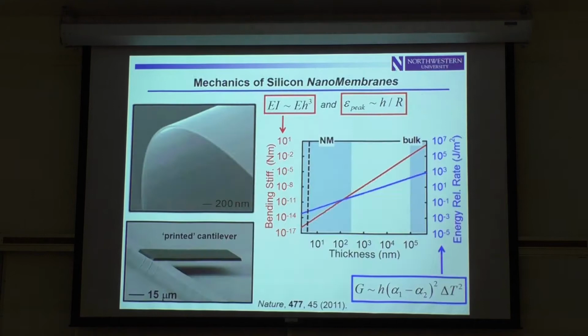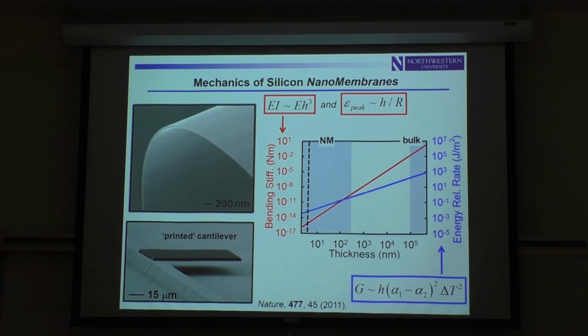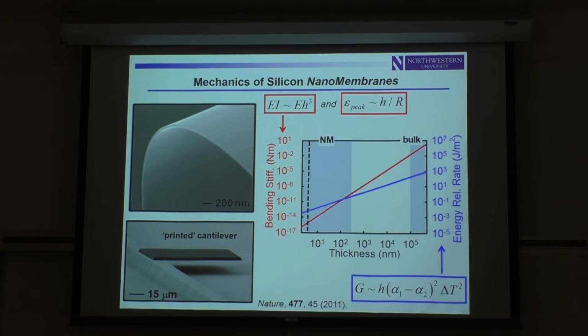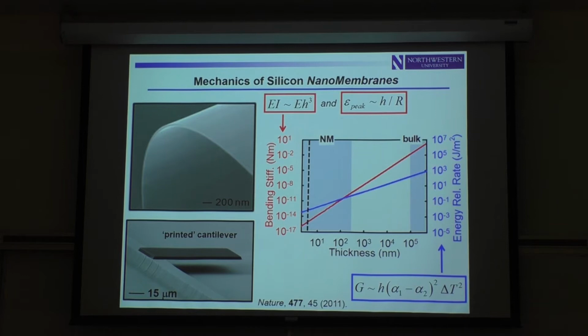And it turns out that there are ways to recast silicon, redeploy it in different geometrical forms, that allow you to bypass a lot of those limitations from the standpoint of mechanics and geometry. And really two concepts here, and I'll just highlight them. It's just very trivial physics, but with really important implications. And so if you think about silicon not in the form of wafers, but in the form of these ultra-thin membranes, so maybe 20 nanometers in thickness, 50 nanometers, kind of in that realm, it really changes the way you think about the material from an intuitive mechanical standpoint, simply because of very simple physics scaling laws.